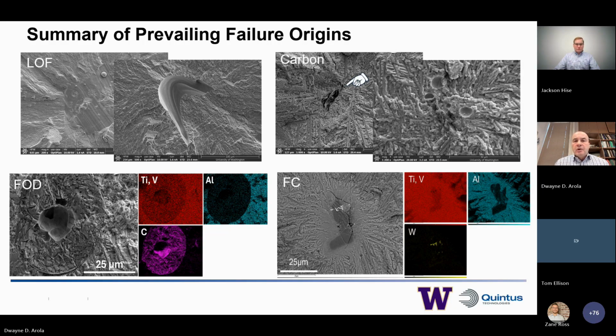Carbon FOD, certainly present, and sometimes small bubbles on the boundaries of the individual carbon defects. We saw FOD, foreign object debris. In this case, that could be an individual particle. You could see in this case, aluminum deficient, higher in carbon.